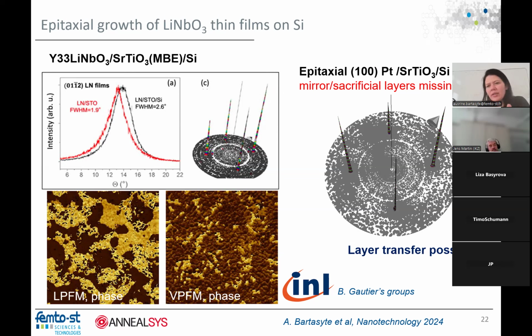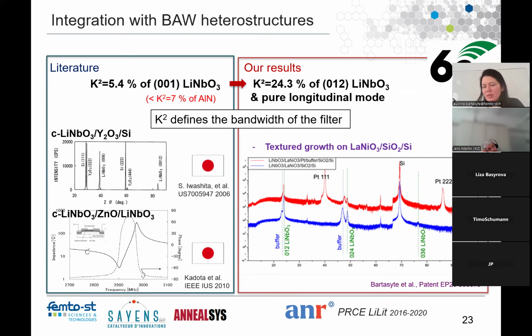So then at the end we found another seed layer, which would allow us to grow this orientation on any substrate, and it was lanthanum nickelate. Lanthanum nickelate is also a very well-known material in the perovskite community, and is used as a seed layer for PZT and so on. So we can sputter 012 orientation. I'm sorry, I'm speaking in hexagonal unit cell. For people who use pseudo-cubic, it would be 100 orientation. Because it's a trigonal material like lithium niobate, I always use hexagonal unit cell. So we can grow 012 lanthanum nickelate just by sputtering, and we can sputter on any substrate, it goes naturally in this orientation.